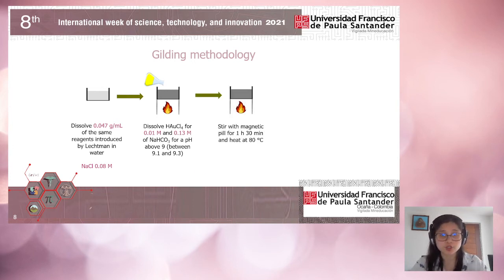Then, to have a homogeneous mixture solution, what we did was to use a magnetic stirrer for 1 hour and 30 minutes. Then we heat the solution to 80 degrees Celsius in order to have a hot temperature for the process. To determine this temperature, we based it on literature that said that an optimal temperature was between 80 and 90 degrees Celsius. At 90 degrees Celsius, the water starts evaporating faster, and that gave us non-uniform gilding. Therefore, we decided to use 80 degrees Celsius.